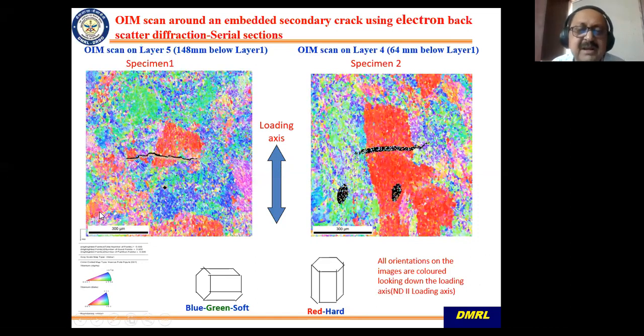I will show you the microtexture. You don't have to understand too much, but you can see the microtexture is almost like microstructure. You can understand it much more as compared to XRD microtextures, which are slightly difficult to understand. You can see this crack. These are two different samples tested separately, and you can see the whole crack is kind of embedded.